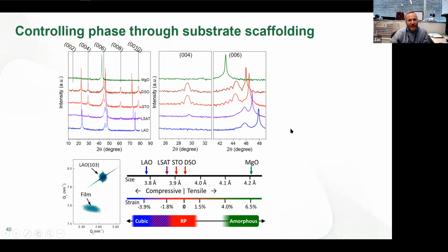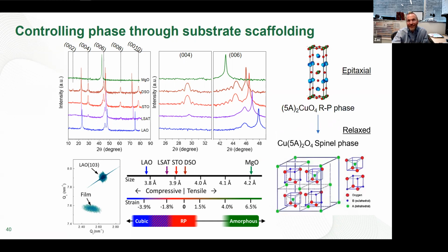We're getting something cubic that's popping up. So this is what we see: when you're controlling the strain, you basically can't control it all the way, because if you have a certain seeding site on your substrate, you will end up getting a different crystal type growing. And so what we see is it looks like we've got a spinel. It looks like somehow this is flipped over and we end up with some kind of a cubic spinel.